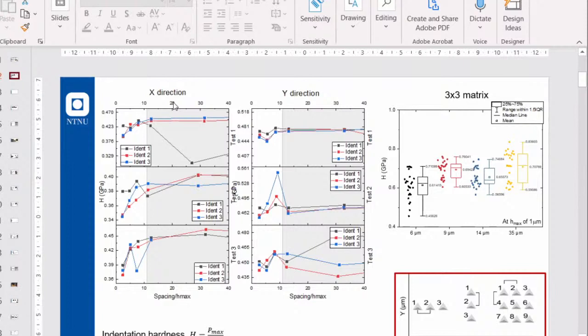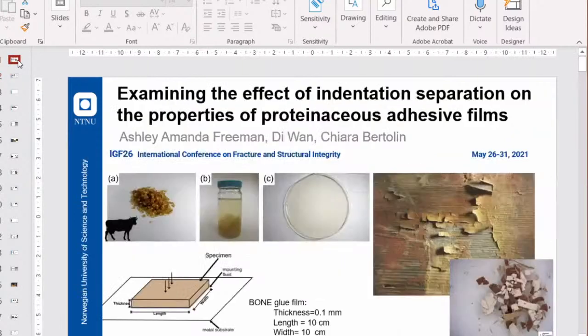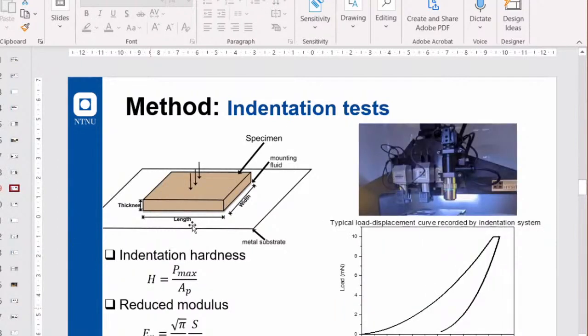I see that the total thickness of the layer is 100 micron, isn't it? Yes. And yeah, a few information about the loading parameters. I mean, maximum load, type of indenter, and so on. So the maximum load for these tests was 10 millinewtons. We did a linear loading of 1 second and then a 0.5 second pause. So I can show you the actual schematic because it'll be easier to say it when you see it. So here, a linear loading of 1 second, 0.5 pause, and then a linear unloading of 1 second. So then the max load of 10 millinewtons.